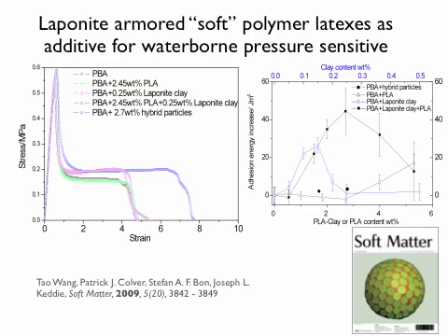What we think, but we don't know, is that when you stretch this fiber, you will start to distort this armored particle, and the clay platelets pop off the particle, which dissipates energy, which allows it to stretch further before it breaks. But we haven't got exact experimental proof, so that's something that still needs to be done. So this is a nice application for these types of structures.